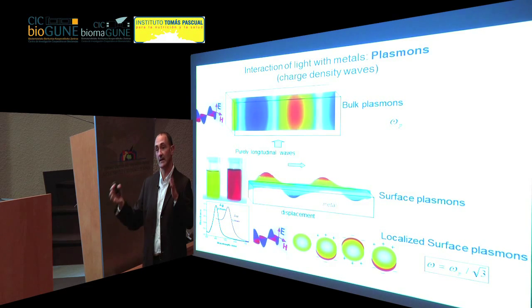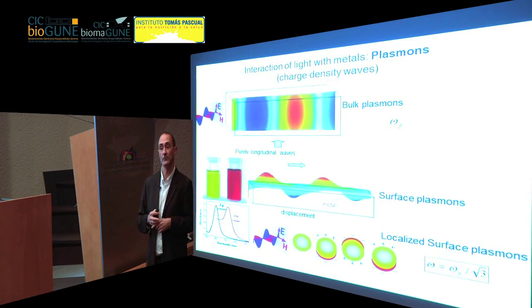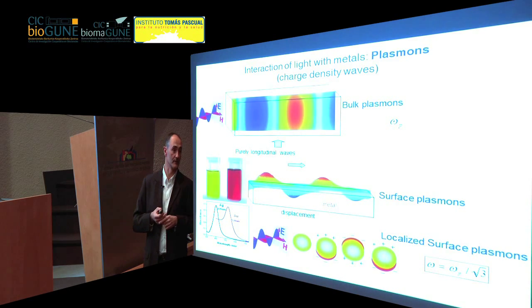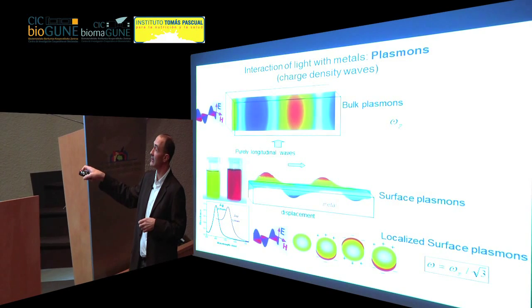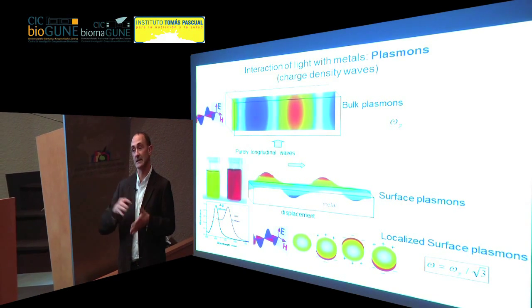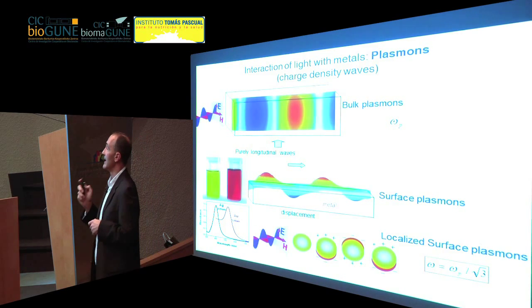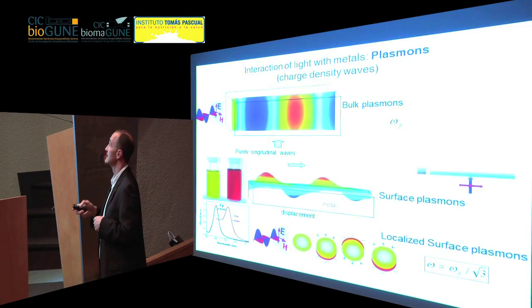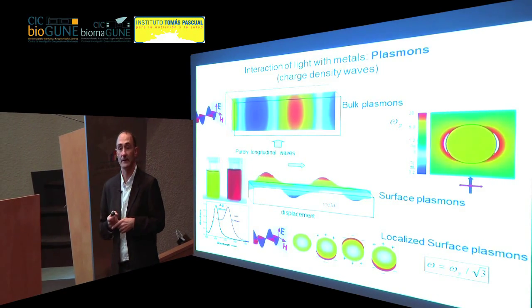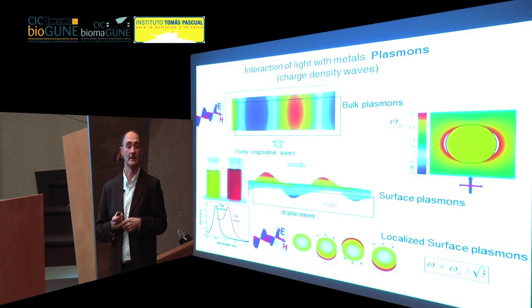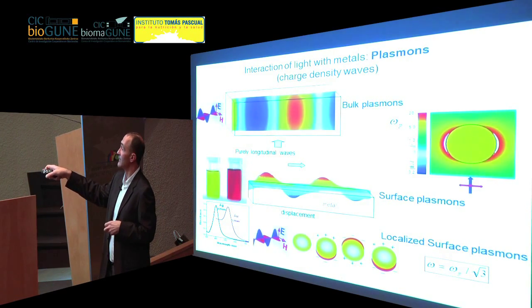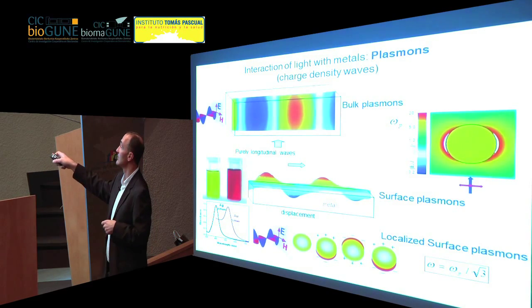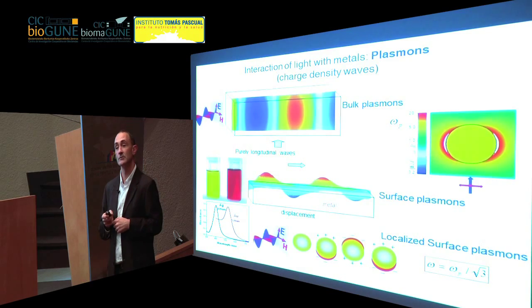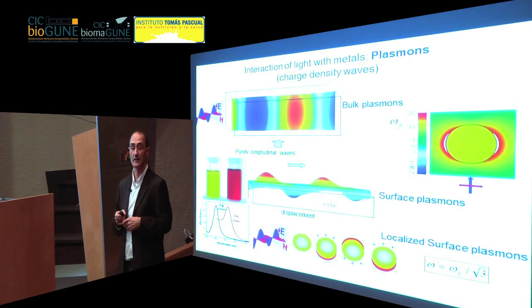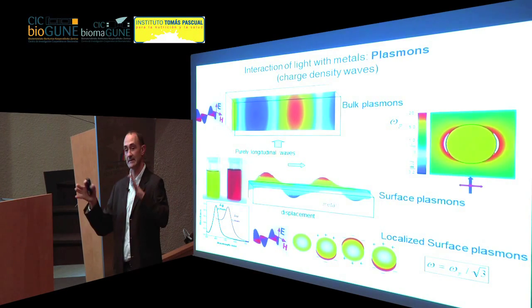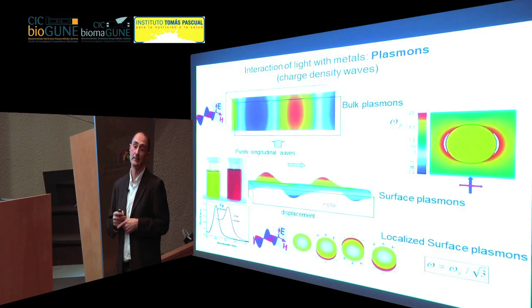This is what we used to say until about 10 years ago, when we started to be able to make nanoparticles with different morphologies routinely, and then we cannot say anymore that colloidal gold is red or colloidal silver is yellow, because this changes a lot with the morphology of the particles. Another interesting phenomenon that takes place when this happens is that you also excite a very large electric field at the surface, in the near field of the metallic surface. So apart from creating this large absorption, you also create a high electric field, and this can be used to affect chemistry taking place in the neighborhood of this metallic surface. So this is the basis of all that we do in the nanoplasmonics field.